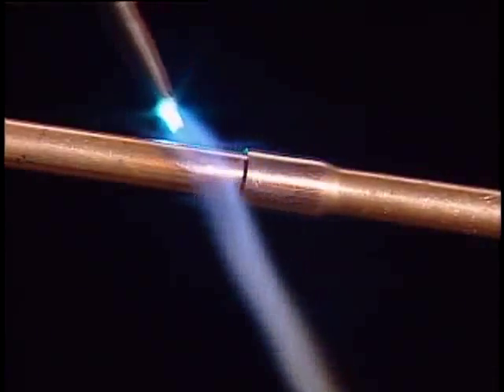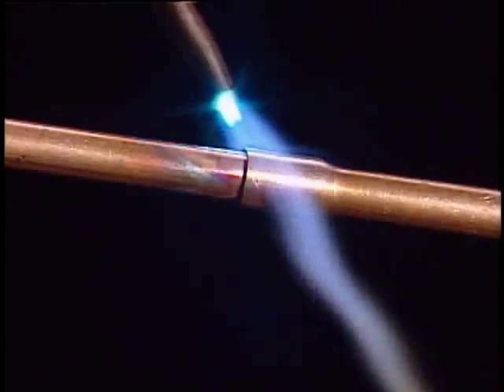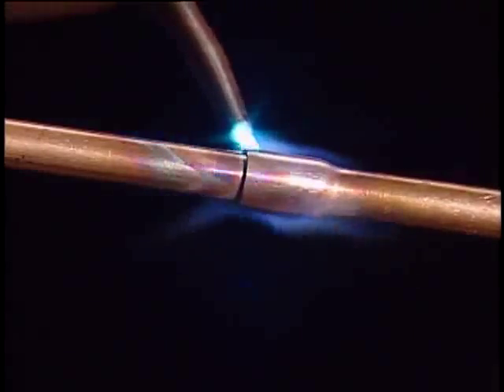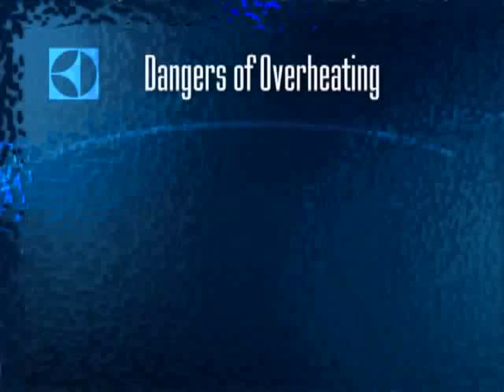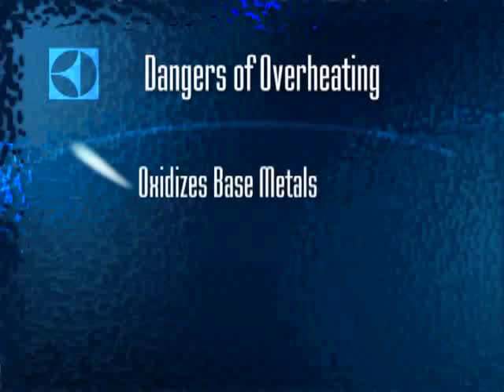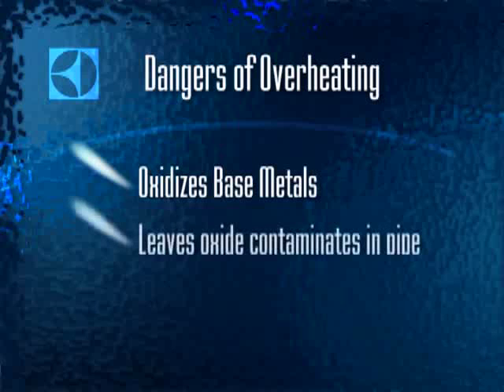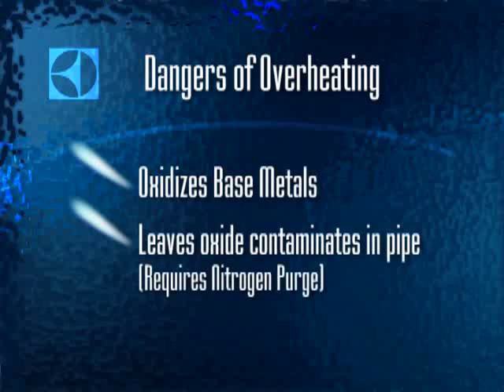Then apply heat to the fitting, keeping the torch in constant motion to adequately heat both the tube and the fitting. But don't overheat. Overheating causes a variety of problems. First, it oxidizes the base metals, and the oxidation interferes with the flow of filler metal into the joint. Second, oxides inside the joint will flake off and potentially block the cap tube. Only a nitrogen purge will have enough pressure to loosen and eliminate all of those oxides.